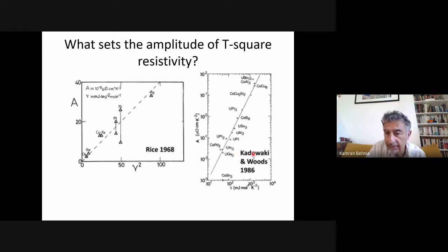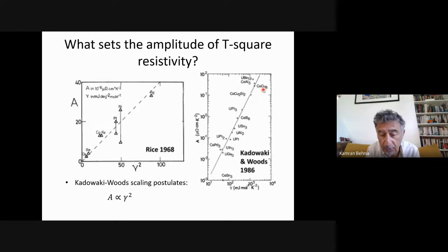18 years after, Kadowaki and Woods made this plot very famous because they plotted A versus gamma in a log-log plot. This is a linear plot. Here you have a log-log plot. And they found that actually the same correlation with a different prefactor is valid for heavy fermion systems. I am going to call it Kadowaki-Woods scaling, even if Rice was the first, because this is now what has been popular in the heavy fermion community, among which I grew up, actually.